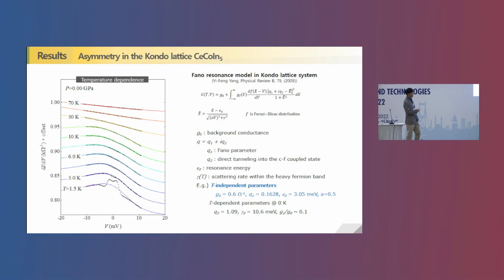And then in order to quantitatively analyze this differential conductance, we use the so-called Fano resonance model in the Kondo lattice system. This conductance curve consists of two parts. The first term is the so-called background conductance. The second term is the interference term that gives rise to this asymmetry. The Fano parameter q is a complex number, and the second complex number is direct tunneling into the c-f coupled state. And epsilon sub 0 is the so-called resonance energy.